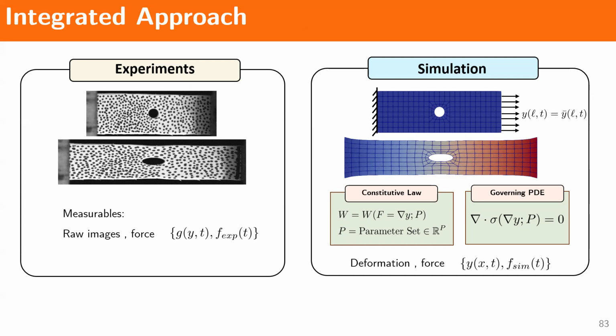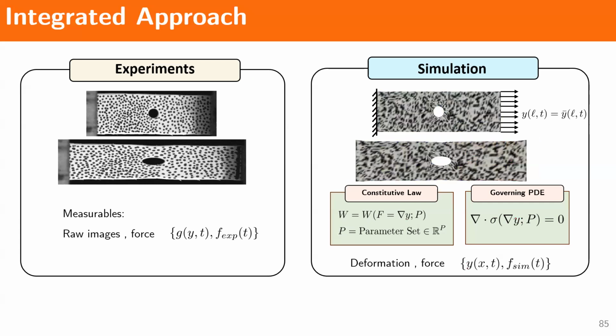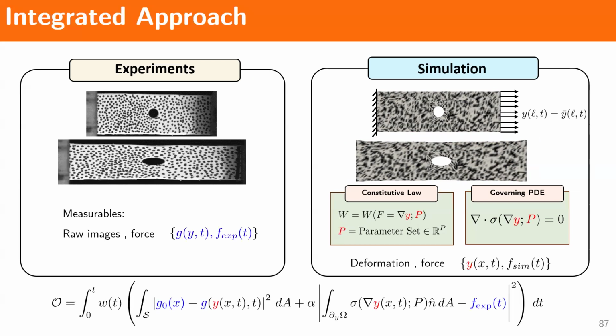So you can run your simulation and you can get your displacement field as well as your simulated force at the boundary. Our raw data is still our raw images. So what we can do here is warp the simulated displacement with the speckle pattern that we started off with in our experiments. So we can warp the displacement with the experimental speckle pattern. Now you can get a series of simulated images. So now we can compare your simulated images with your experimental images. So here this is our objective. It's an optimization problem. Our objective will be the difference between our simulated and experimental images, as well as simulated and experimental forces.